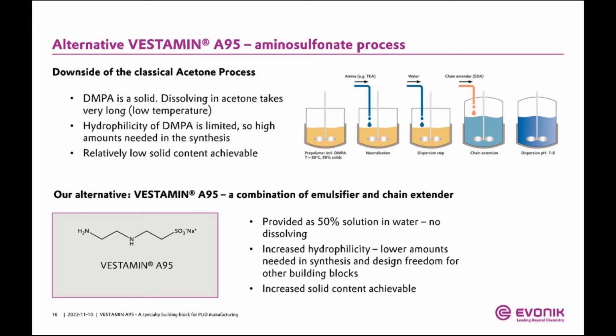So both are factors of the DMPA where we think this is not the ideal solution, and this is where we want to present you the alternative. We call it VESTAMIN A95. This is a combined emulsifier, so it has also hydrophilic groups. In this case, it's a sulfonic acid salt, and it is combined with a chain extender, so it is also a diamine. So it is emulsifier and chain extender in the same molecule. One big advantage is it is provided already as a 50% solution in water, so you don't have this lengthy dissolving step anymore.